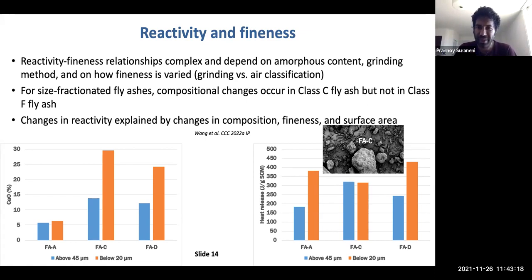So let's talk first about air classification, or specifically in this case, sieving and size fractionated fly ashes. We size fractionated 3 particular fly ashes, A, C, and D. We separated out the below 20 micron fraction and the above 45 micron fraction. In A, which is a class F fly ash, there is no difference if you size classify based on the chemical composition. The calcium oxide content is very similar. On the other hand, if you take the 2 class C fly ashes, which are C and D, here it is very interesting because the above 45 micron fraction, the coarse fraction, would be a class F fly ash. On the other hand, the fine fraction, which is the below 20 microns, becomes a class C fly ash.